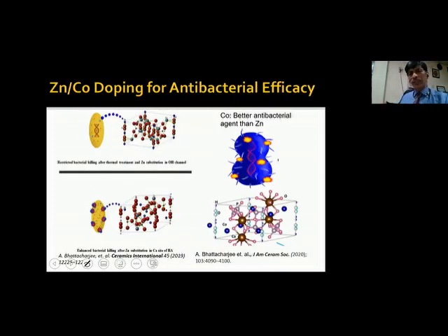We also went on, very recently, to start doping hydroxyapatite itself with zinc, with cobalt, and also a mixture of those two. We also tried adding copper, which I have not presented, but we see that cobalt is a better antibacterial agent. And secondly, and more importantly, I can dope zinc either in an OH channel or a calcium channel. So hydroxyapatite is Ca10(PO4)6(OH)2. So I can put zinc on the calcium side or on the OH side. But I see that if it goes in the OH,